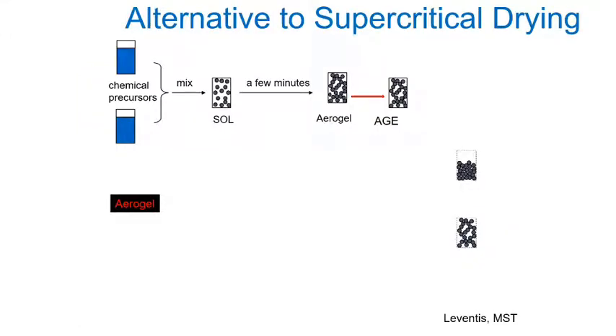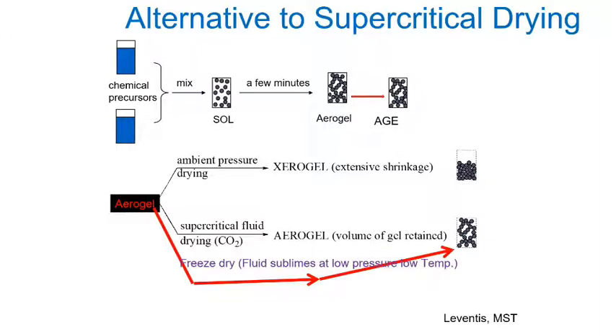So again, we have the process going, but we want to figure out whether we can do other things. Can we actually avoid supercritical dryers, which are very expensive, and try something else? One thing is we can use freeze drying, where you basically freeze the sample, reduce the pressure, and then what happens to the fluid? It's going to sublimate. If you freeze and then lower the temperature and the pressure, you get a sublimation process going.